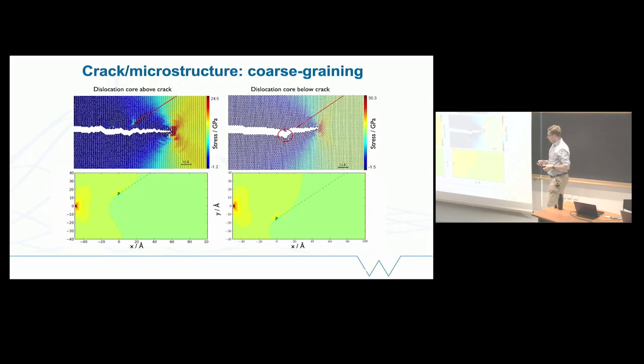So these are expensive simulations because every step is involving quantum mechanics. But if you do a few of them, the idea is you can make a representative model at larger scale. So a very simple continuum model, for example, where you look around and you measure elastic energy, and it's informed by simulations that you've done here. This is roughly the same setup as the one that we just saw, where we traveled for a bit along the stacking fault. So these kinds of ideas allow you to access mesoscale or coarse grain scale and feed into engineering problems using atomistic input, where you could never get there directly by running the simulation.